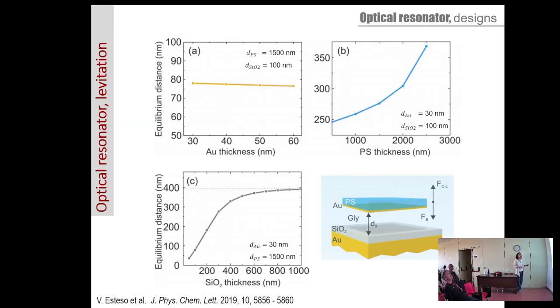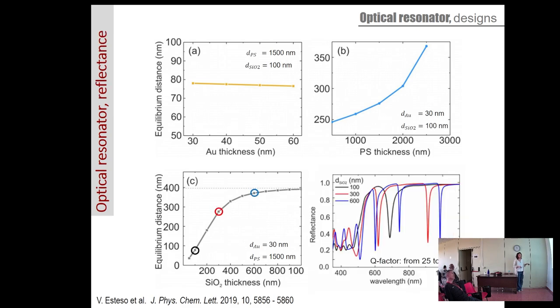Okay, so now we said, can we do something with these optical resonators? So we try to tune and modify the distance between the two mirrors by changing the thickness of the gold film, the polystyrene, or the silica film. These are the three cases. And in all cases, we could tune the equilibrium distance from several tens of nanometers to several hundreds of nanometers.